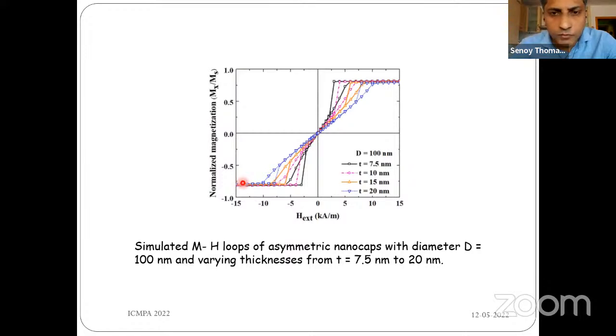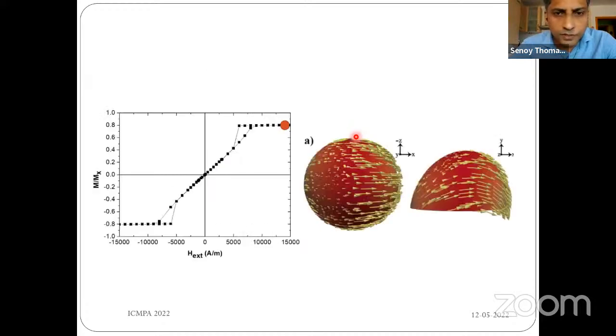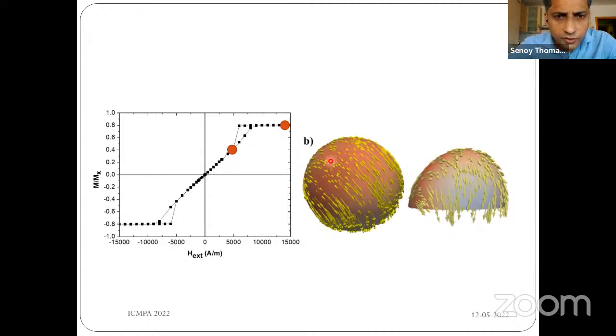So in order to have more insight into the reversal process, we recorded the spin configurations at different fields. And what we observed is that at very high positive fields, the system adopts an onion spin configuration. And once the field is reduced, the system turns to a C state, which is basically arising due to the shape anisotropy associated with the asymmetry of the system.